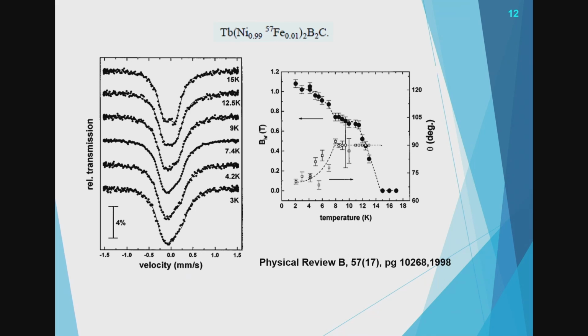So Dauber had started his PhD by that time, and we were already working with borocarbides, which was a boom in the field of condensed matter, this kind of materials. And Dauber did a nice work in many of them. I put one example here that is terbium. Dauber doped with 1% of iron this terbium nickel boron 2 carbon, and he found the same kind of asymmetry of the spectra as a function of temperature.